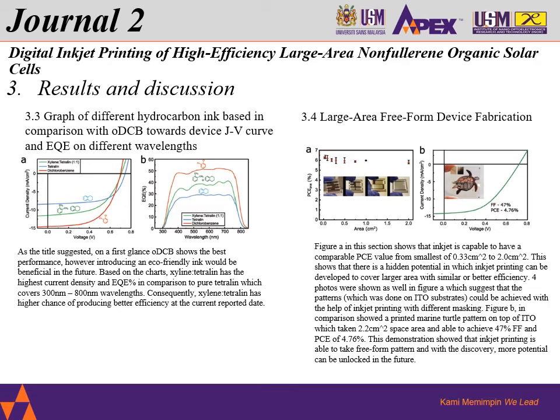And then the figure over here, or the chart, is the JV curve of this marine turtle printed. This is also a solar cell, which is very interesting. This shows that inkjet printing opens up more opportunities to create beautiful so-called paintings that are also usable for solar cells. Even though this was printed on a 2.2 centimeters squared area, it is still able to achieve around 47% fill factor and 4.76% PCE. So in short, this can create more potential in the future.